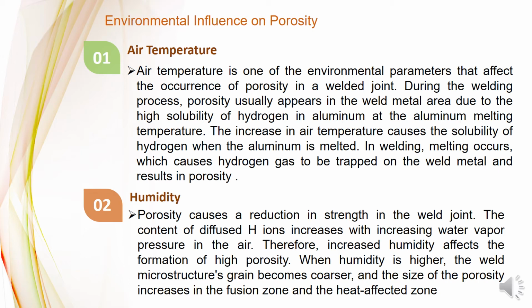Number 2, humidity. Porosity causes a reduction in strength in the weld joint. The content of diffused H ions increases with increasing water vapor pressure in the air. Therefore, increased humidity affects the formation of high porosity. When humidity is higher, the weld microstructure grain becomes coarser, and the size of the porosity increases in the fusion zone and the heat affected zone.